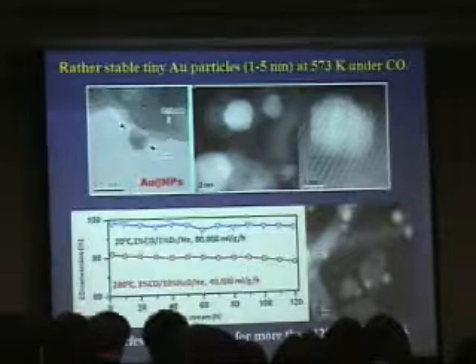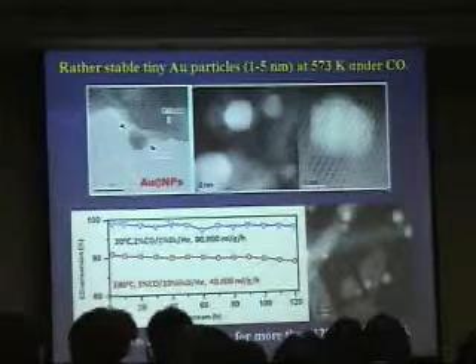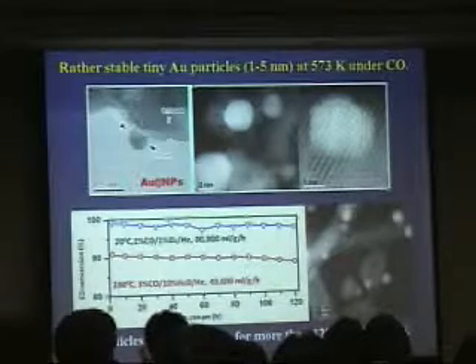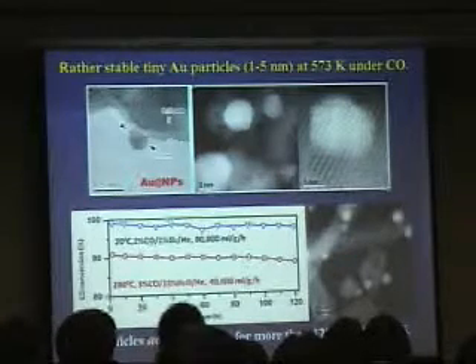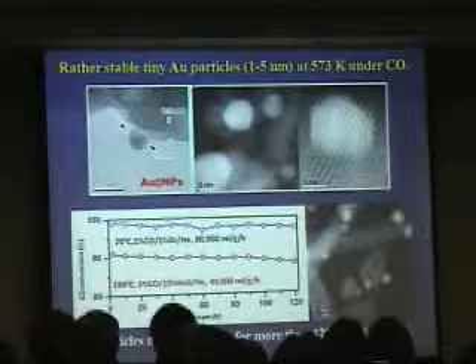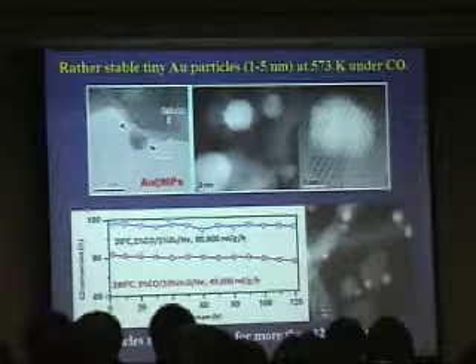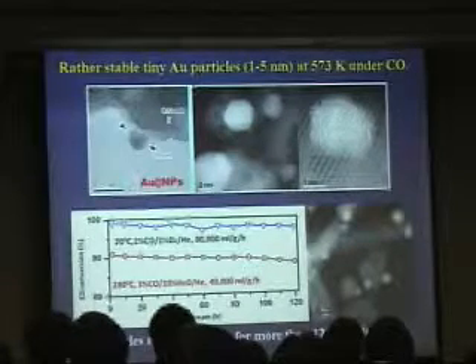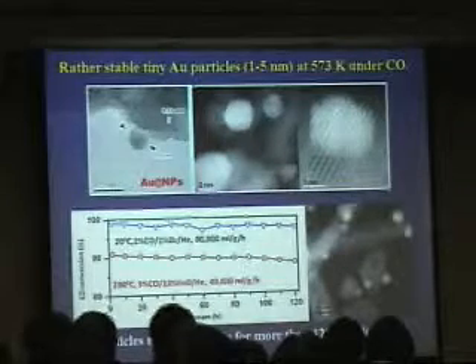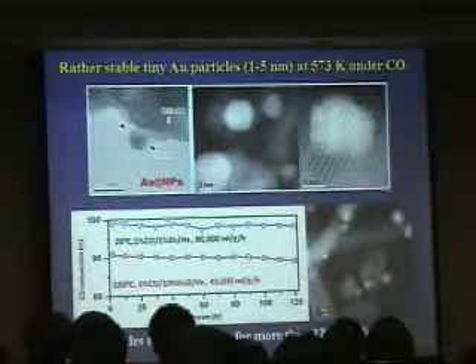Even after the reaction, at this point you take out the sample, you find gold particles still less than 5 nanometers, still strongly bonded on the support. So this is very important for gold nanocatalysis, because from the beginning, for almost 3 decades, gold is very active for a lot of reactions. But the problem is that sintering of the gold particles occurs rapidly, even for room temperature CO oxidation.